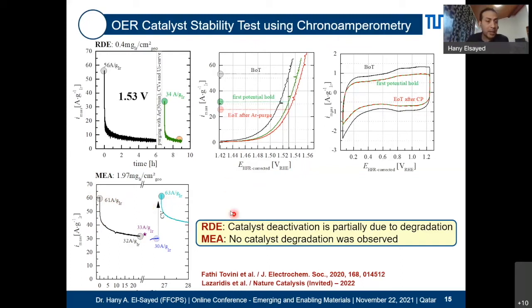So now you can see this. Again, the conclusion from RDE is that it's not a stable catalyst. From MEA, it's an extremely stable catalyst.